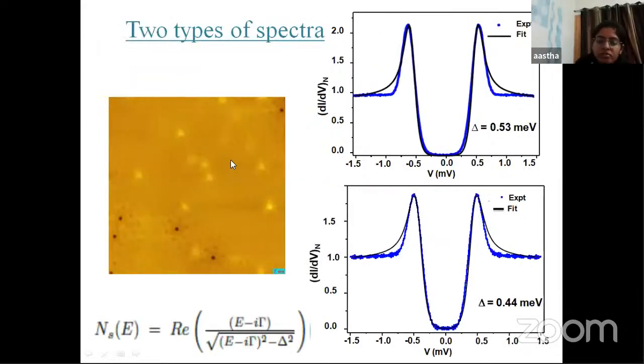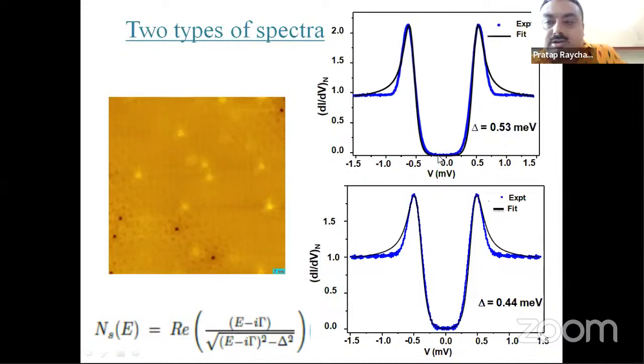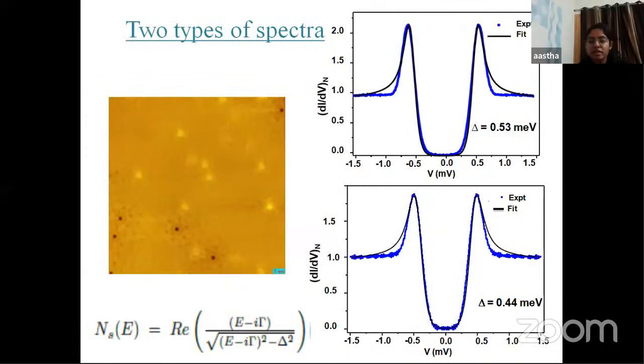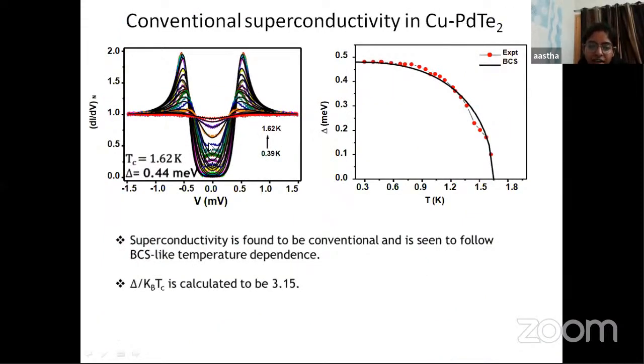So actually, if we look at this spectra, although that was crowded, at T equals 0, we did not observe any deviation of the fit from the experimental data. Well, here you are seeing a large deviation above the coherence peak, which is again unusual. Yeah, this deviation is observed at a bias higher than the coherence peaks. However, we observed a slight zero bias peak at certain temperatures higher than the lowest temperature. At elevated temperatures, this was observed, and this might be due to some unconventional order parameter.